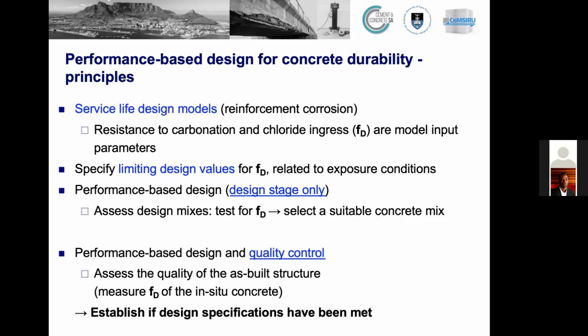And the most relevant factors that cause reinforcement corrosion worldwide and also in South Africa are carbonation and chloride ingress. So we now define test values that characterize how the concrete is resistant against carbonation or chloride ingress in the same way as we use the cube test to define how the concrete might behave in the structure under loading. Once we have defined those test values and once we have test methods, we can specify limiting values for durability for certain exposure conditions.